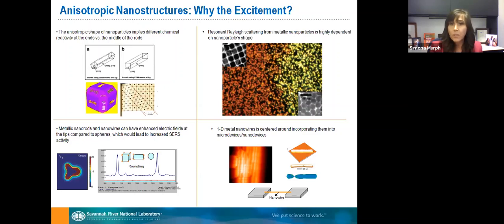At the same time, if you're looking here at the top of these slides, you see that even if you have, for example, gold cubes versus gold hexagons, looking at the Rayleigh scattering, they can glow orange or they can glow yellow. This is important because if you want, for example, to put a drug on these nanoparticles, you can actually track to see if they go inside, if they go to the brain or do they go to the heart. Just by having the same composition but a different shape, you can actually use them for tracking.